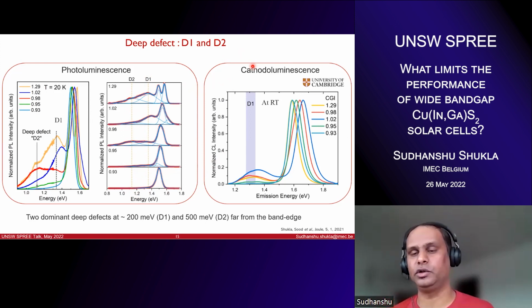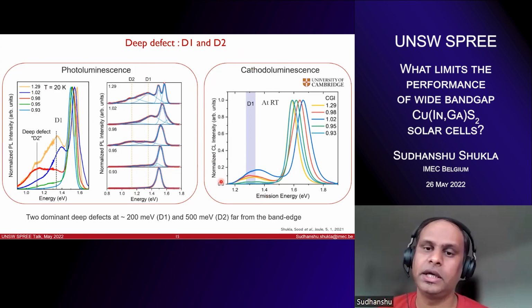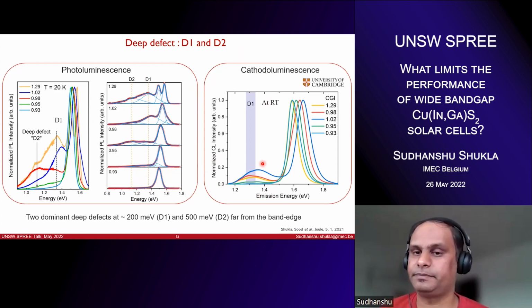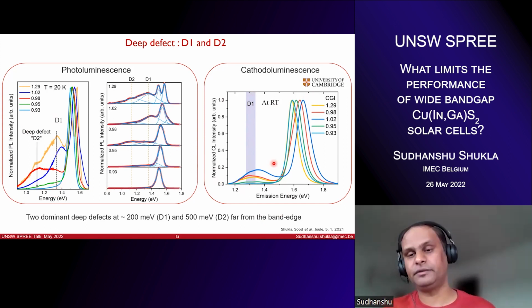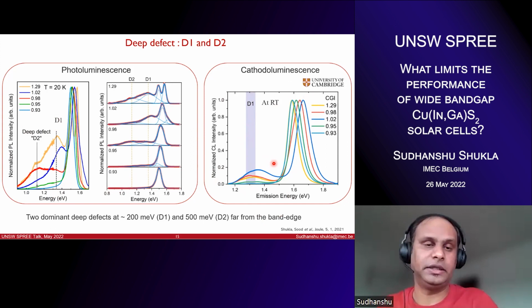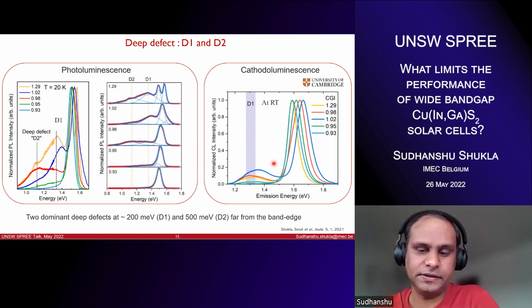Then after this observation, we reached out to our colleagues, the experts at the University of Cambridge. They do cathodoluminescence, a very nice technique to get high resolution spatial information about the recombination. So here they are also normalized to this band edge, and what you see is the appearance of this D1, at least the position where the D1 band that we observed in the PL. So we do see a deep defect signature in PL and also in the cathodoluminescence.